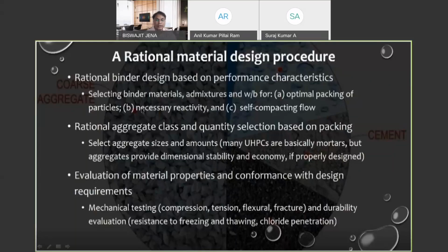So in that case, what size of aggregates can I use? I cannot use larger than 25 mm aggregates because this won't flow, because the space between the rebar is probably 10 or 15 mm. So I need very small aggregates to go in, and what kind of aggregates can you use? How do I choose those family of aggregates? These are the second challenges we have. So choosing the binder, choosing the aggregates, and then proportioning the mix so that all the contrasting requirements are satisfied. We'll go one by one.